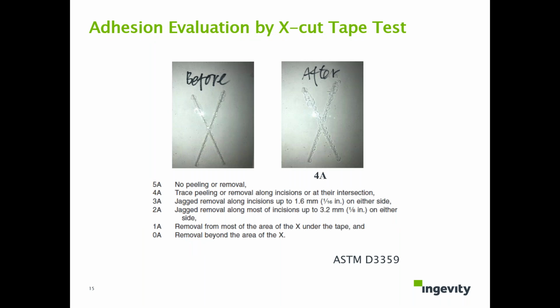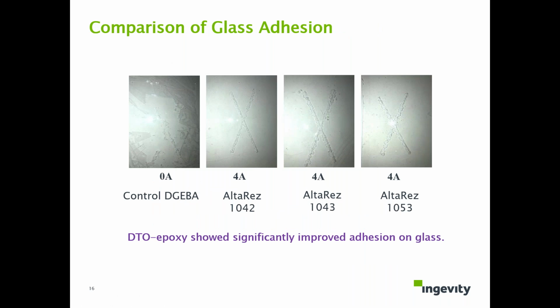We also looked at adhesion evaluation by the ASTM cross-hatch tape test. 0A represents totally failed, without much adhesion on the substrate. 5A represents best adhesion on the substrate. So here is a comparison of glass adhesion, the benchmark and our DTO epoxy. You can see the control, DGEBA, is another name for EPON 828. It totally failed on glass adhesion in this specific condition of hardener and post-cure. Our DTO epoxy significantly improved adhesion on glass, from a 0A benchmark to 4A.